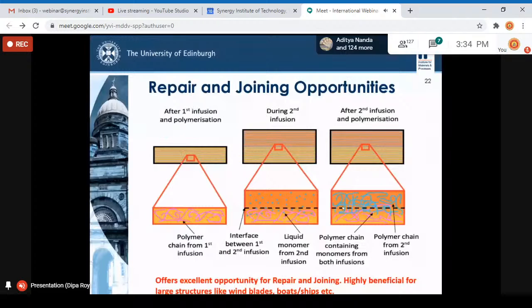So this is enhancing these properties. Instead of having a weak bond line, we have a very strong bond line, with this semi-IPN kind of formation. This was theoretical, we thought this was going to happen, but with the experimental results we saw exactly the same. So this opens up a very good opportunity for repair and joining of this kind of laminates.